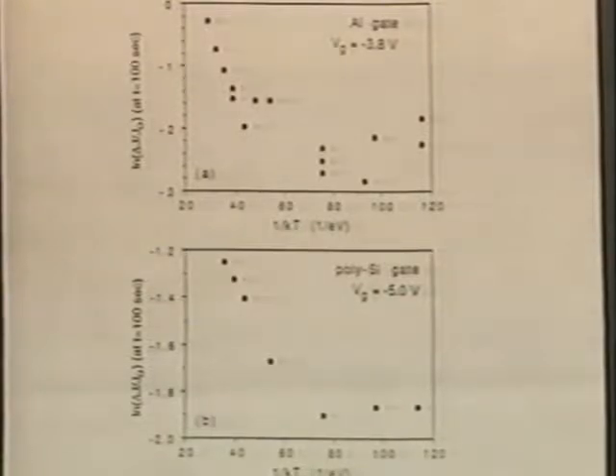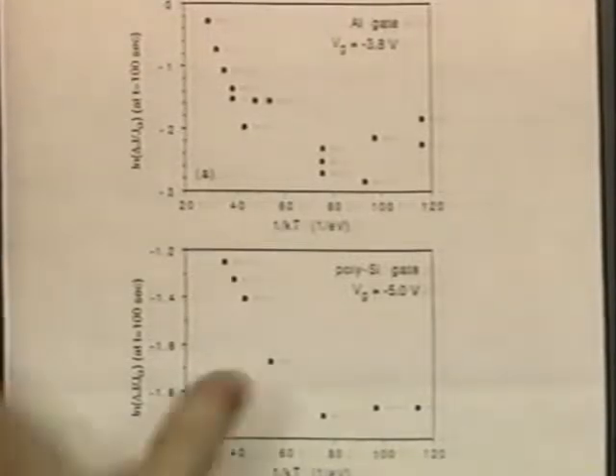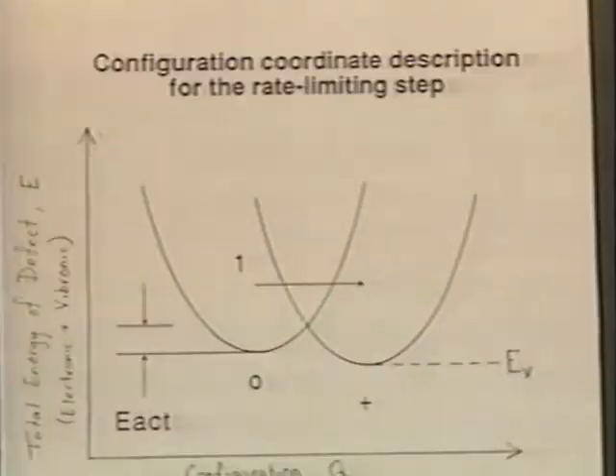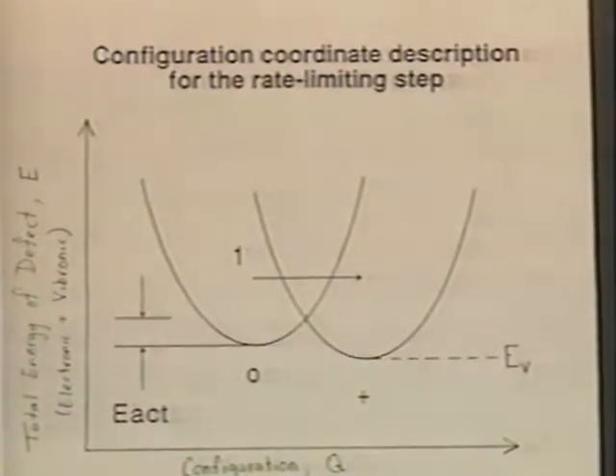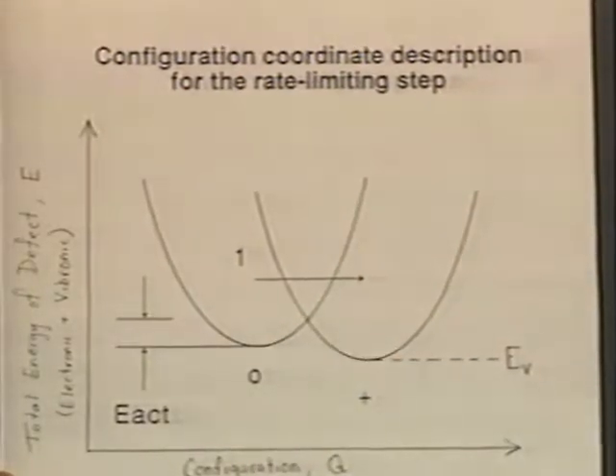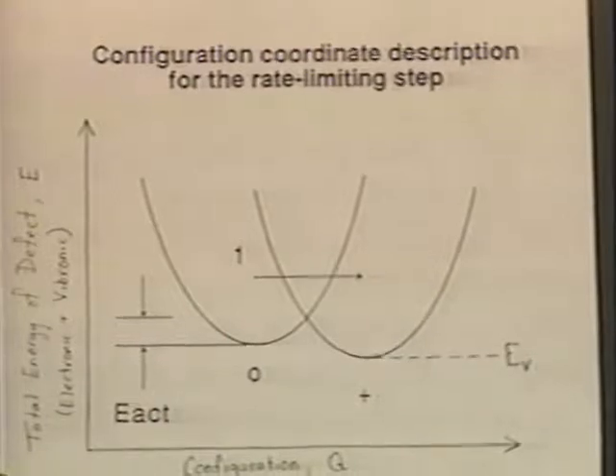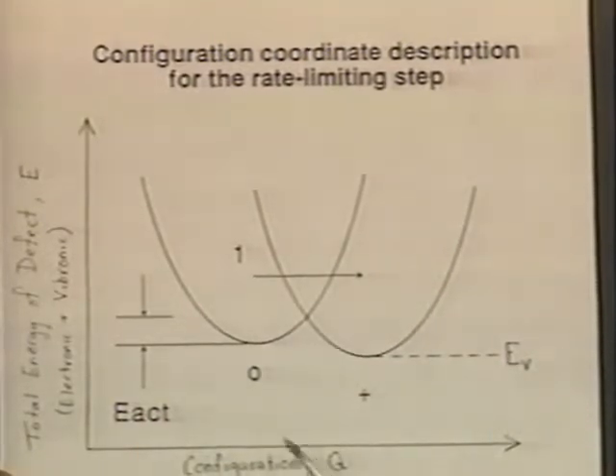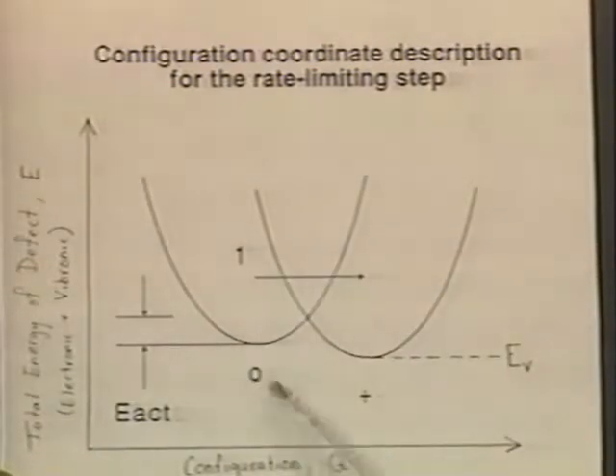Now, to me, what I would say is let's have one mechanism for both temperature regimes. And I'll give you one that I'm familiar with. You need what's called a configuration coordinate description for a defect or defect precursor. Now, think of a defect precursor as, say, a silicon-hydrogen bond. The hydrogen atom is like a mass on a spring. And so you use a harmonic oscillator approximation, and that's what this is here. This is the vibrational energy of a harmonic oscillator in some energy state. And this is the electronic plus vibrational energy because you can reference it to some electronic energy. So you've got a defect that's in a state, and the 0 here means that it's in its neutral state.